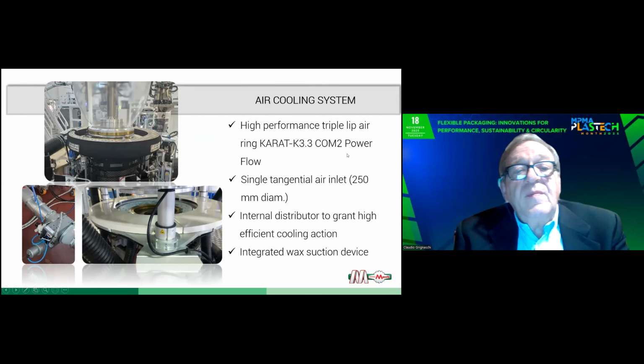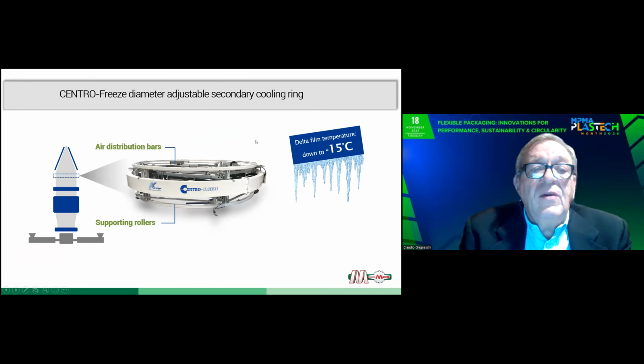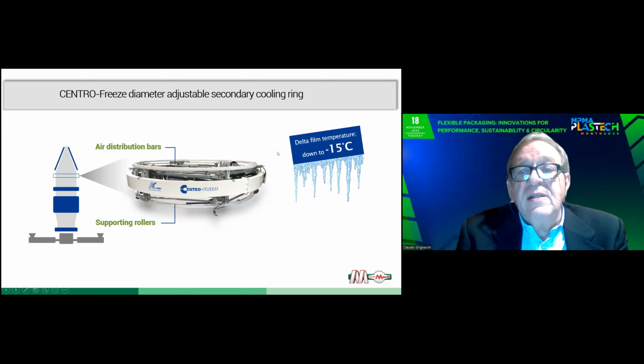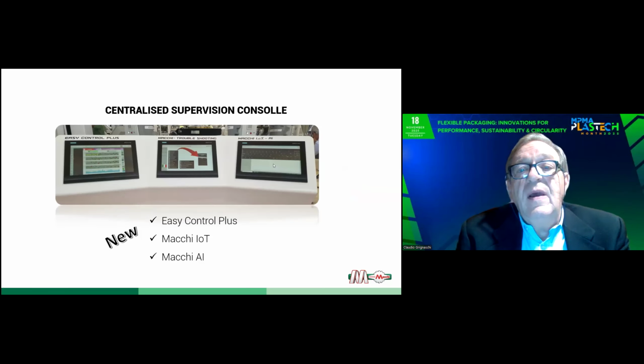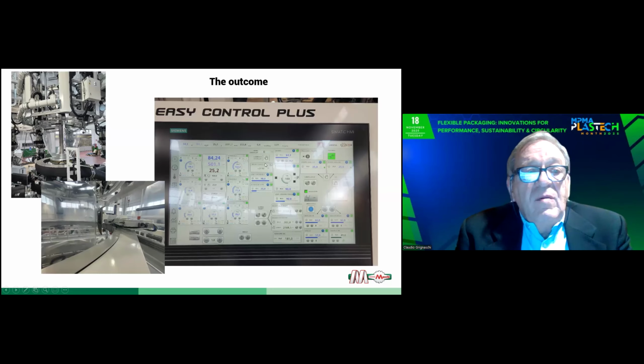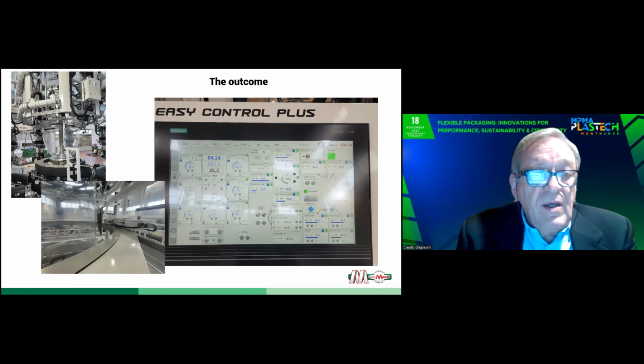The Centrofreeze secondary cooling unit, able to decrease the film temperature by up to 15 degrees centigrade to avoid any possible blocking even with low towers. And our new supervising system, HMI, the new IoT, the troubleshooting, and the artificial intelligence developed by Macchi, which was the result of all those innovations.